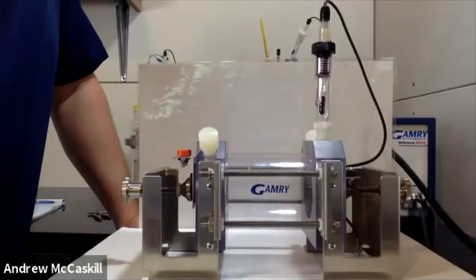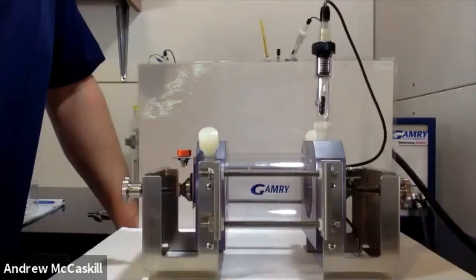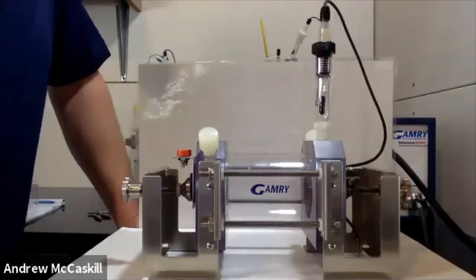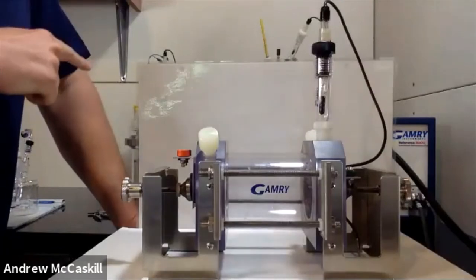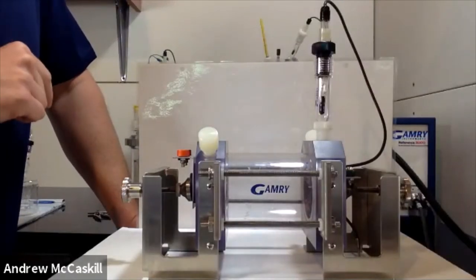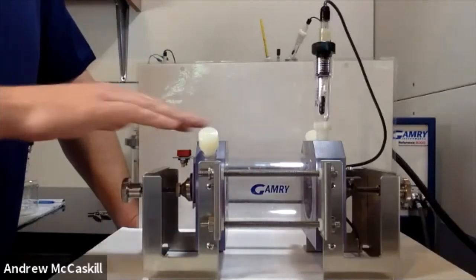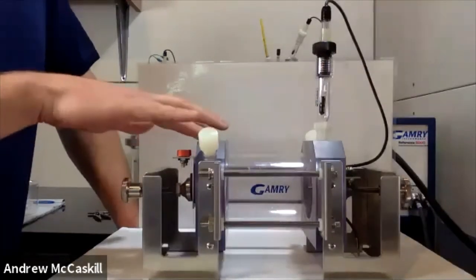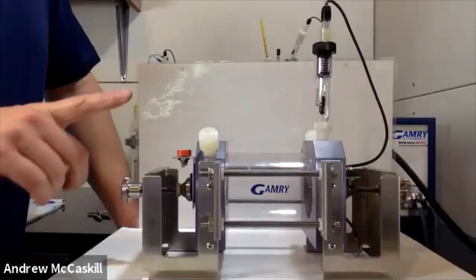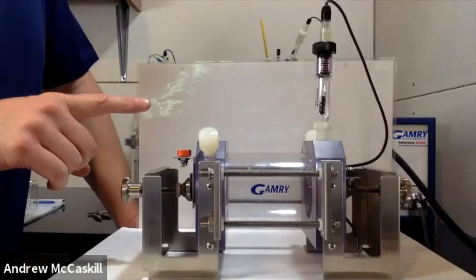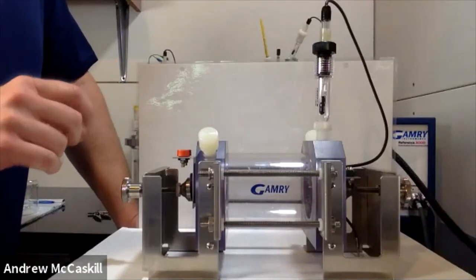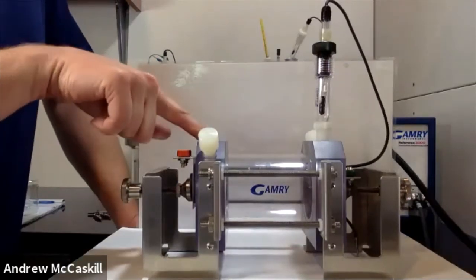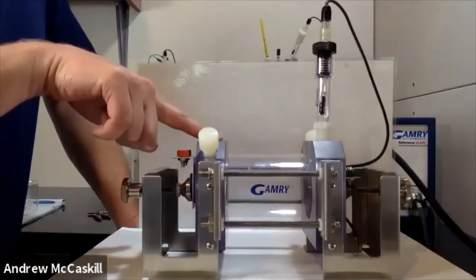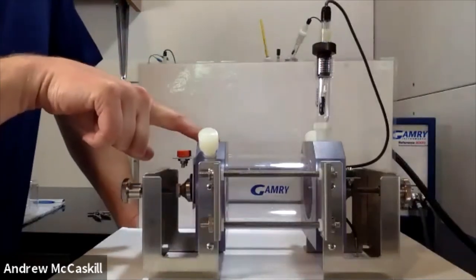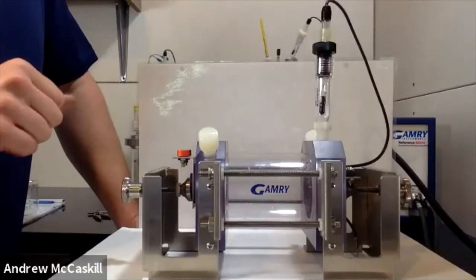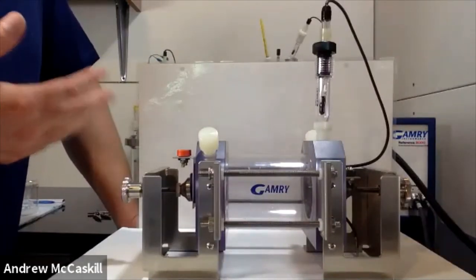For these corrosion experiments, generally the currents are low enough that you're not going to run into much of a situation like that. But you'll see when we get to the next couple cells, the counter electrode is going to have a much larger surface area than the working. But in the case of the paracell here, the surface area is the same. And it's designed that way for a specific reason. When I get into the applications, we can start talking about looking at a galvanic couple, doing ZRA experiments. So for this cell, it's actually designed to have the surface areas as close as possible to one another. But again, depending on your specific experiment, having that larger surface area on the counter electrode might be crucial.